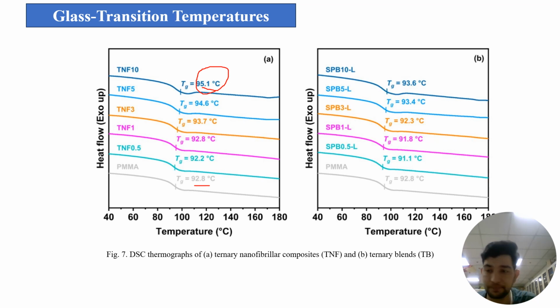Figure 7b: when PEBA was dispersed as spherical particles with EGMA, the Tg remained comparable to that of pure PMMA at all concentrations. Like here, it is the same blend, but here the blend is made to contain fibers, and here there are no fibers. Here the dispersed phase is spherical, while here the dispersed phase is fibers. That's why here Tg increases a little bit more, but here it does not.